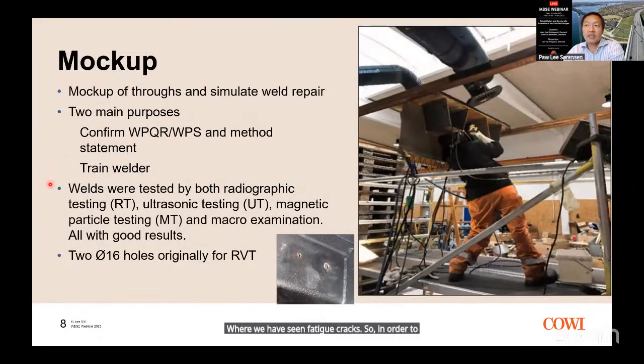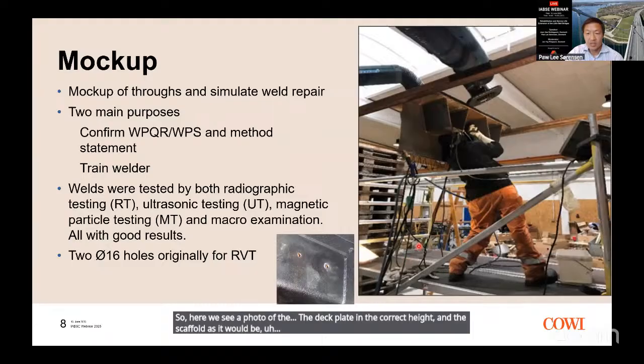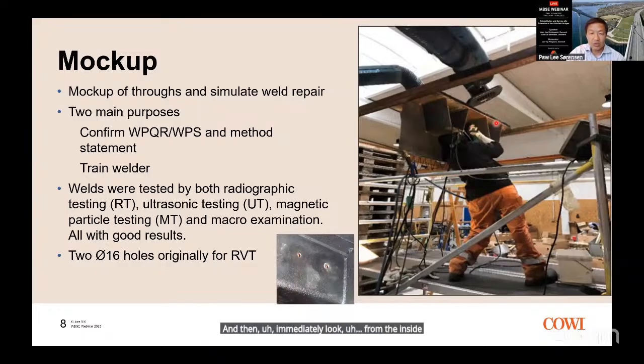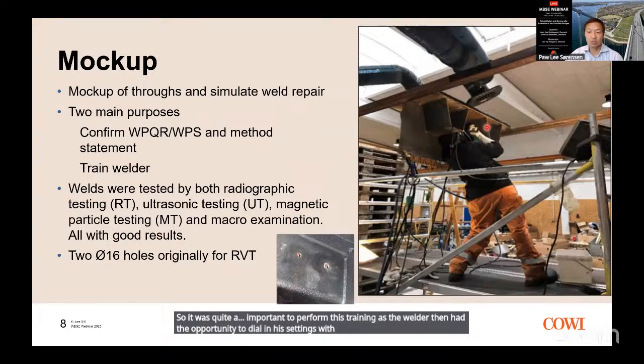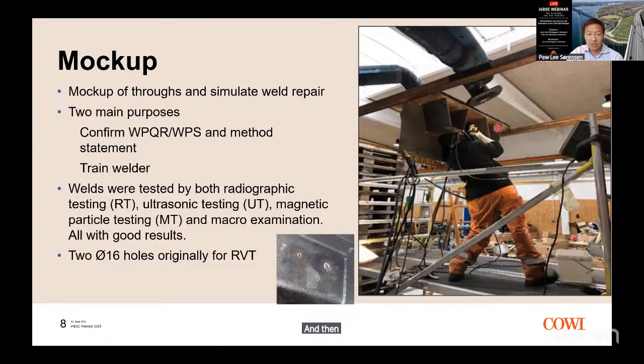So in order to repair these welds, we thought it would be very beneficial to perform a mock-up to simulate the weld repair. The mock-up had 2 purposes. First of all, it was to confirm the WPQR and WPS and the method statement. And secondly, it was to train the welder under realistic conditions. So here we see a photo of the deck plate at the correct height and the scaffold as it would be during the repair. The welder can then perform his weld and then immediately look from the inside at what the result was. So it was quite important to perform this training, as the welder then had the opportunity to dial in his settings with regards to speed and position, etc., and then could look at it quite quickly.